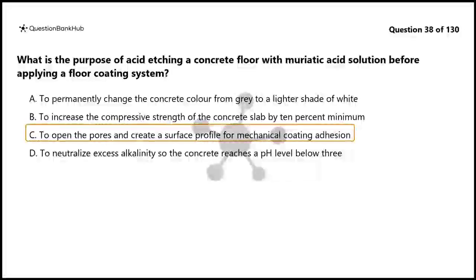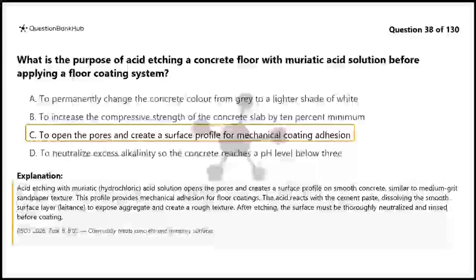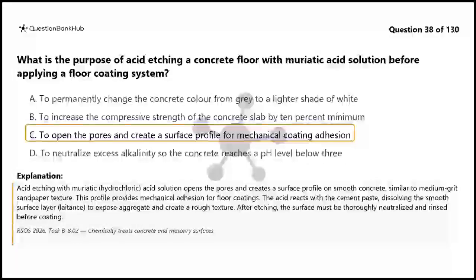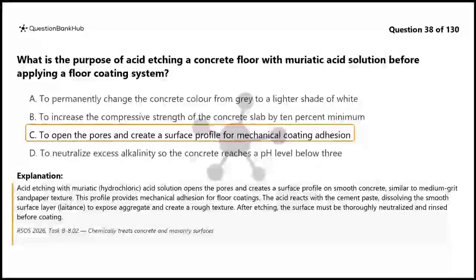The correct answer is C. Acid etching with muriatic, hydrochloric acid solution opens the pores and creates a surface profile on smooth concrete, similar to medium grit sandpaper texture. This profile provides mechanical adhesion for floor coatings. The acid reacts with the cement paste, dissolving the smooth surface layer to expose aggregate and create a rough texture. After etching, the surface must be thoroughly neutralized and rinsed before coating.